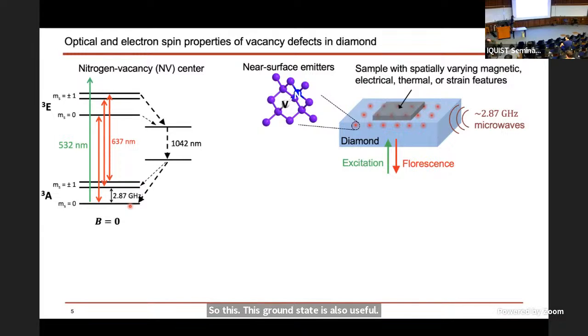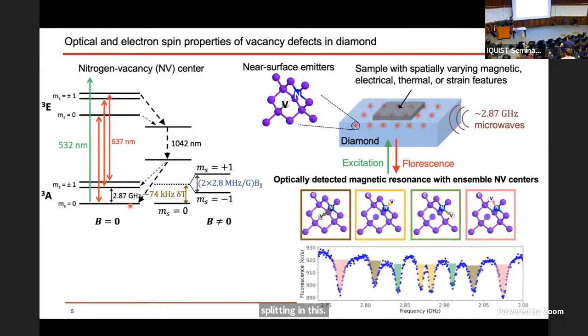The separation between this ms 0 and ms plus or minus 1 is 2.87 gigahertz. In the presence of a magnetic field, you have splitting in this subsystem, and you can actually measure that optically. So this is a spectrum of the magnetic resonance as you're scanning over this transition. And the splitting that you observe is going to be magnetic field dependent.